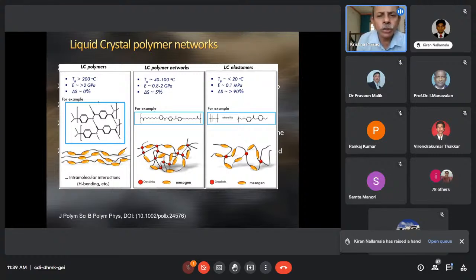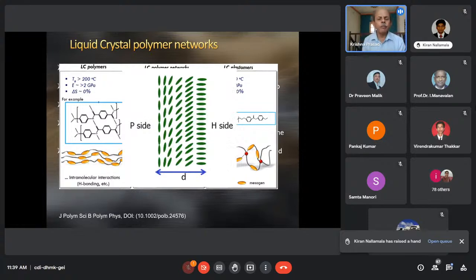So we were working on such systems, and Divya's idea was to have orientation of the liquid crystal polymers which are parallel to the substrate on the P side, and on the other side they are vertical to the substrate, and that's why it is referred to as the H side. And you have a continuous variation, a bend deformation, going from the planar side to the homeotropic side.